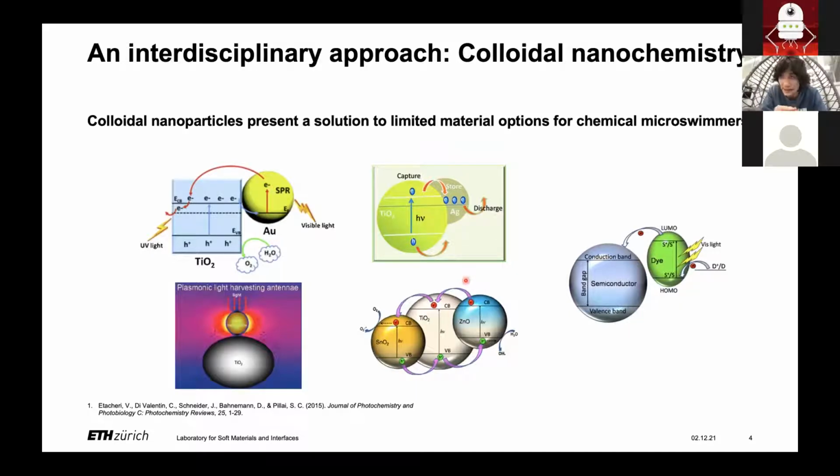Just as an example, with regards to the photochemical system that I'm looking at, you can consider the titania photocatalyst. Already going to nano-size titania is advantageous because you have the advantages of high crystallinity and high specific surface area, which come with using nanoparticles. But in addition to this, you can consider increasing the efficiency of a photocatalyst by introducing co-catalyst metal nanoparticles, which might increase the efficiency, for example, by reducing the rate of charge recombination or introducing heterojunctions, or even extending the wavelength of absorption of a photocatalyst, so for titania from UV to visible light, by introducing plasmonic nanomaterials that might be able to inject hot electrons into the photocatalyst itself.